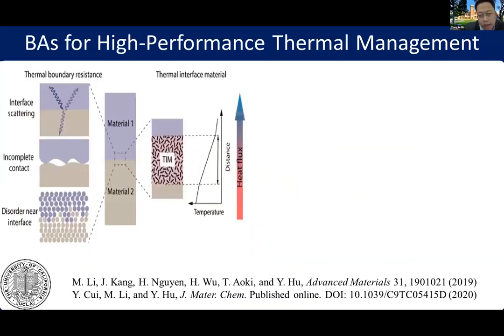So with these materials in hand, now look back to the initial motivation for thermal management. I want to look at the fundamental mechanisms that contribute to the near junction thermal resistance. The near junction thermal resistance could come from several different parts. It can come from interface scattering, which is intrinsic due to the energy spectrum mismatch across the interface. It would exist even with atomically perfect interfaces. It could also be contributed by incomplete contacts, such as voids and surface and interface roughness that reduce the effective contact area. The other contribution to thermal resistance is the disorder near interfaces.